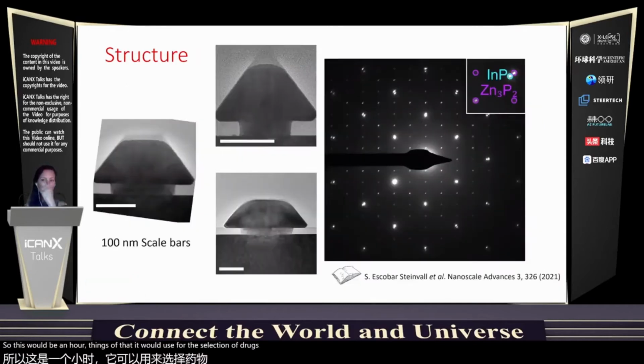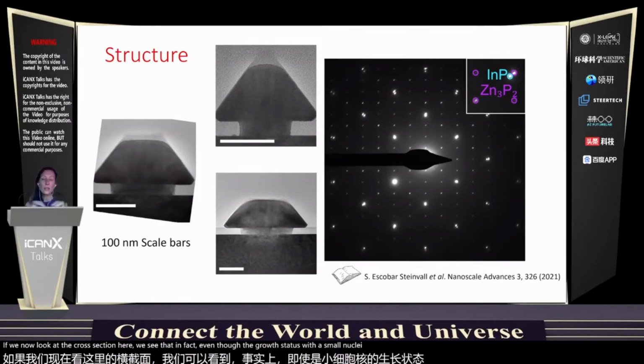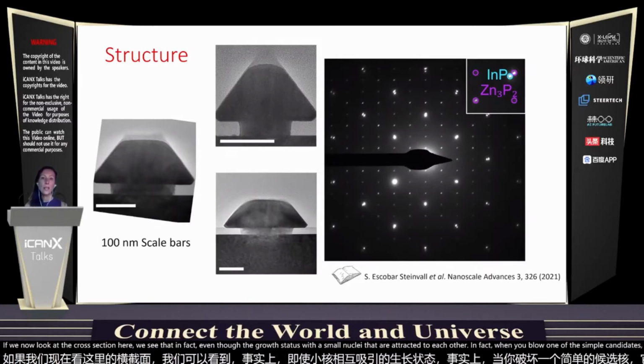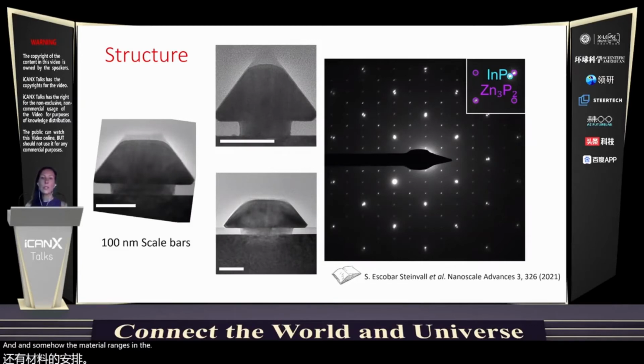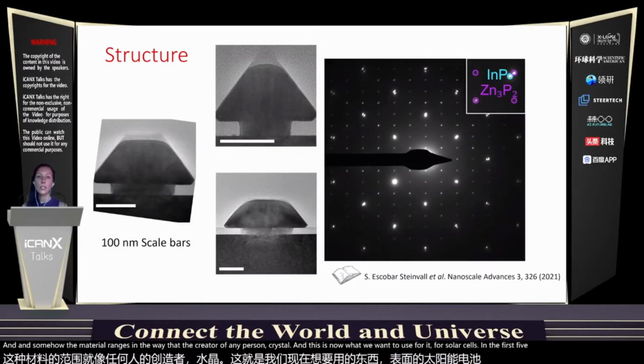If we now look at the cross-section TEM, we see that, even though the growth starts with small nuclei that are not connected to each other, when you grow one of the simple pyramids, it's a single crystal. Somehow the material arranges in a way that you create a very perfect crystal. And this is what we want to use for solar cells in zinc phosphide. For us, I think this is the highest potential material for Earth-abundant solar cells.